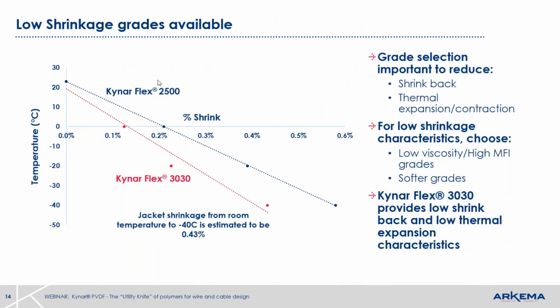Shrinkage, we always get this question, especially from fiber customers. What grade should we choose to have a low cable jacket shrinkage? Years ago, we had developed Kynar Flex 2500. Its shrinkage rate is around 0.6%. This is measured from room temperature all the way down to -40 C. So it shrinks at around 0.6%. But of late, we've developed this new heterogeneous grade, Kynar Flex 3030, and its shrinkage is about 0.4%. So it gives the best low temperature shrinkage, coefficient of thermal expansion available in PVDF.